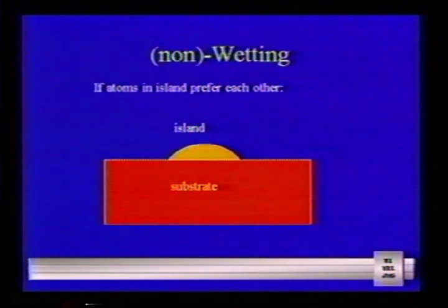But in crystal growth, it turns out that if you go to high temperatures, it's very unusual that something wets the substrate. It usually likes to form blobs, and if you give it enough motion, it will form these large blobs and not a nice uniform film. So you have to play a game where you give the atoms enough mobility to move a little bit to form the step flow, but not enough mobility to ball up and form these blobs on the surface.